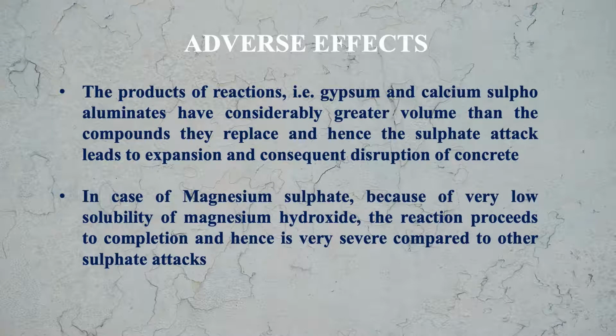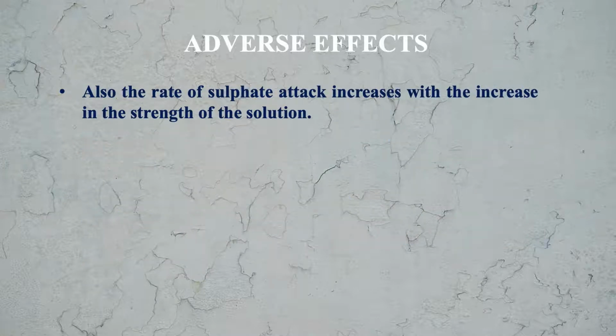In case of magnesium sulfate, because of very low solubility of magnesium hydroxide, the reaction proceeds to completion and hence is very severe compared to other sulfate attacks. Means the effect of magnesium sulfate is more severe in comparison to the other sulfate attacks. Also, the rate of sulfate attack increases with the increase in the strength of the solution. Means as the strength of solution of these sulfate compounds increases, this attack will increase on the concrete.